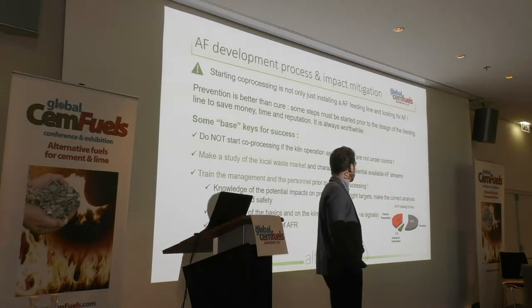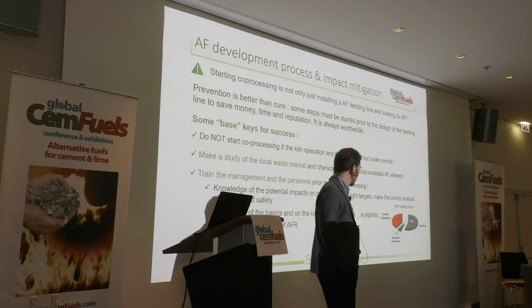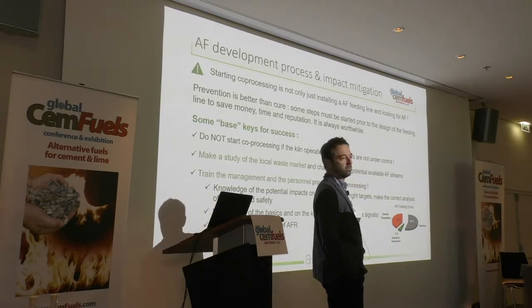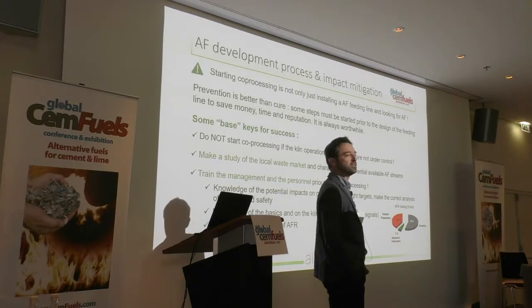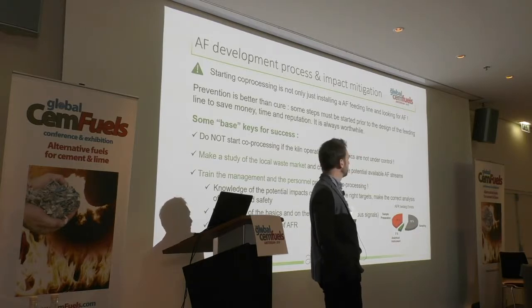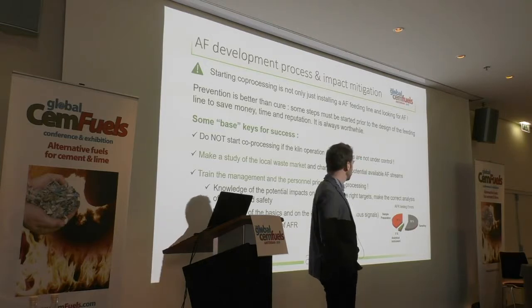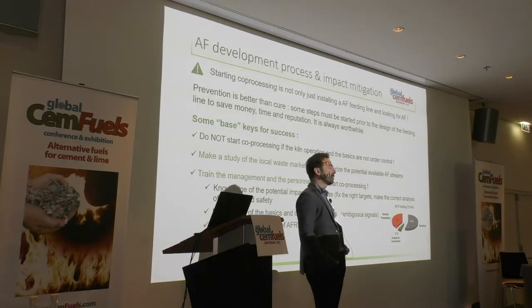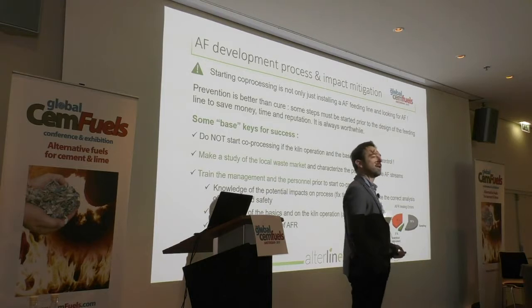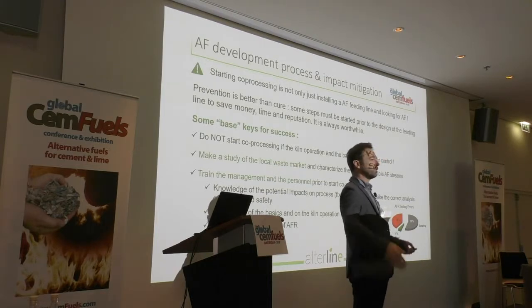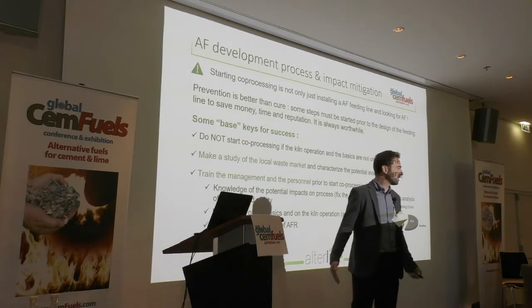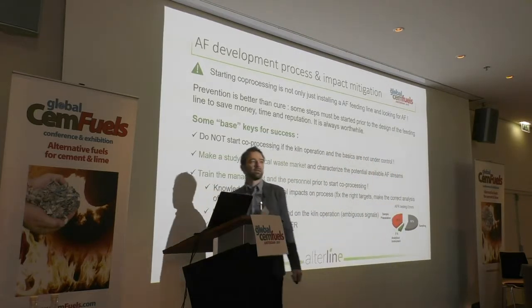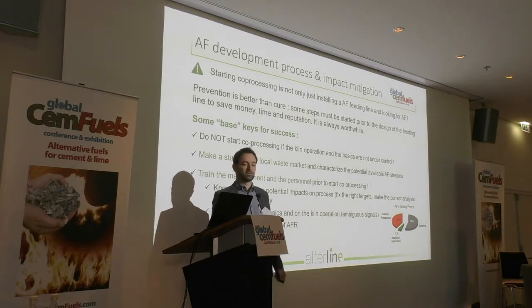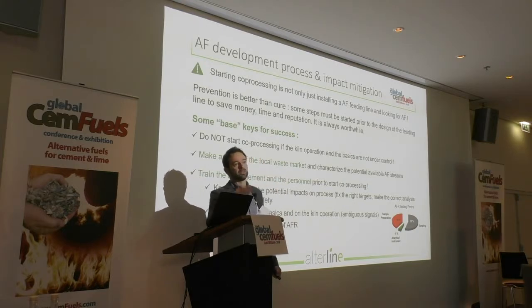Some studies were made in Holcim group when I was in Holcim, and only 5% of the error of analysis of alternative fuel were due to the analysis. It was mainly sampling, 55%, and preparation of the sample, 40%. And there are a lot of plants with a very nice alternative fuel lab, and they have SRF and they have no lab shredder. So they cannot prepare anything correctly, and they cannot sample adequately the material to have something representative. So you really need to make it with a systematic and pragmatic approach.